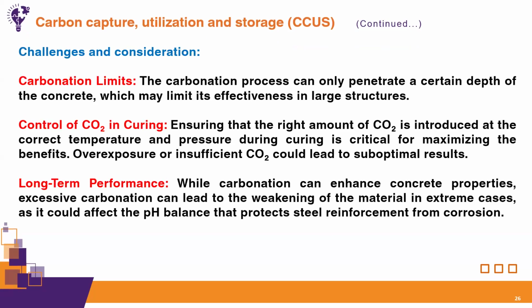So now what are the challenges and considerations? There are a lot of challenges in adopting this technology, especially carbon capturing, utilization, and storage. Some of the challenges are the carbonation limit. The carbonation process can only penetrate a certain depth. So if we cure our concrete in the curing environment, this carbon can penetrate up to a certain depth. So there will be a limitation on its effectiveness in large structures. This is one of the limitations.